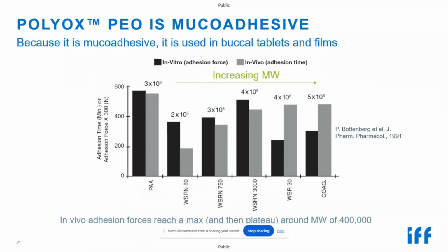The in vivo data shows an increase in mucoadhesion as the molecular weight of PEO increases from 200,000 to 5 million. Around 400,000, there seems to be a plateau where increasing the molecular weight is not imparting significantly higher adhesion properties.